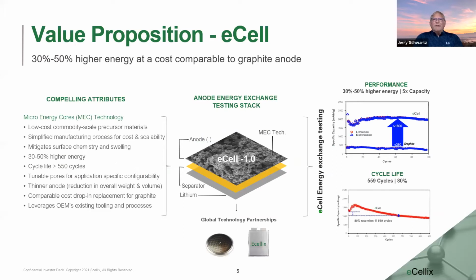Where we're very different is that rather than nano engineering, building up with nano components from the ground up, we start with a large format silicon in the micron scale and do an etching process where we end up with a porous structure of silicon, pure silicon actually, 100% silicon, with a very thin carbon layer around it. This allows us to do a couple of things.